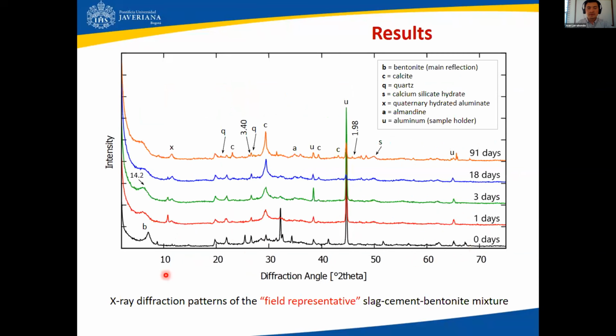Now, what you're looking at now are the results of the field representative slag-cement-bentonite mixture that we tested. So what you see here are 5 stacked patterns, one for each moment in time within a window of 3 months. So we have data for 0 days, that is pre-hydration. And then we have data for 1 day, 3 day, 18 day, and 91 day hydration period, and curing under 100% relative humidity conditions. So of course there is a lot of data here, and I'm gonna break it down for you in just a second.